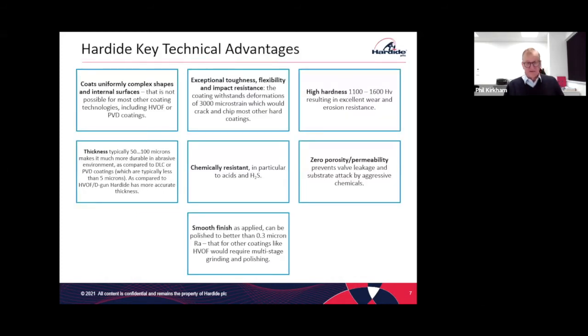So if we just move on again to the technical advantages, because this is why the coating is used. It's the technical features of the coating that are very important. I keep saying that it coats uniformly complex shapes and internal surfaces, and this is probably one of the main features of the coating that is why people are keen to use it. It's not possible with other similar coating technologies, including the more popular ones like HVOF, which is a high velocity oxy-fuel tungsten carbide coating, which is applied by effectively a flame spray gun, so it can only coat the parts you can actually see. And PVD, which is physical vapor deposition, as opposed to our chemical vapor deposition.